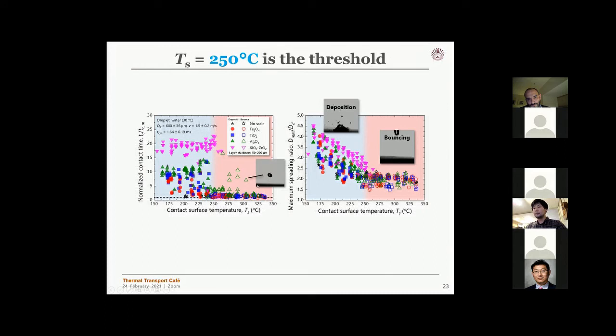Okay, so we had some outliers here, but we actually associated this behavior with the bouncing regime, because if you look at this video, you see the bouncing droplet wants to bounce off the surface, but actually there's some local variation of temperature or roughness. The droplet stayed in contact in a very local area, so we ended up with rather high contact time, but this is still bouncing regime.